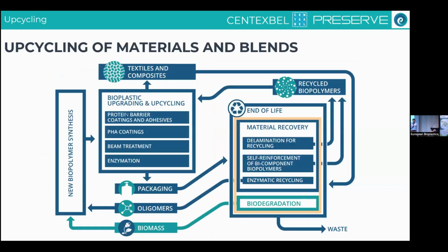First of all, the upcycling. There is a very big scheme of the material flow throughout different demonstrators and different applications, but I want you to focus on the center highlighted in orange, where we see some strategies related to delamination of multi-layer structures, self-reinforcement to look at how we can improve the properties of different polymer blends, and then also enzymatic recycling. So looking at using enzymes to improve the recyclability or improve the biodegradation of different materials.